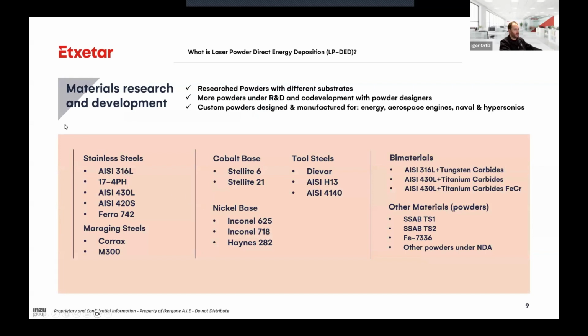We have researched different materials, and these are some of them. We research the same material from different suppliers, and we check the quality of the supplier in different substrates, checking the dilution, no porosity, lack of fusion, and that the quality is enough for the part itself. We have different powders under research, and other industries, energy, aerospace, naval, and hypersonics can be suitable for additive manufacturing or laser powder DED.